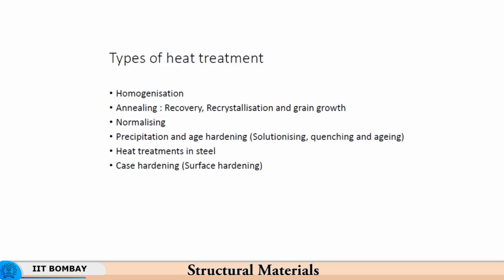crystals or the layers which become solid with a different chemical composition, because the chemical composition of the liquid changes, and what is solidifying is not the mean chemical composition which you had intended. So, naturally, the first crystals or first solids which appear just below the liquidus would be different in terms of chemical composition compared to your intended composition. So, if you have to bring everything to the intended chemical composition, you need to homogenize the material by heating it to a sufficiently high temperature and leaving it for a very long time, so that the diffusion of these atoms takes place, and therefore it becomes a uniform distribution of the alloying elements.